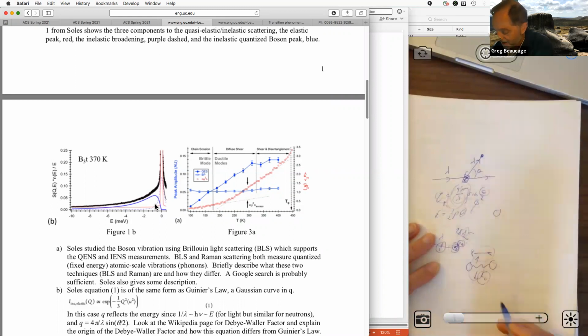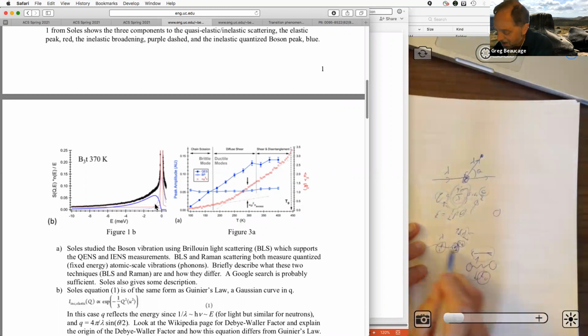So if the beam comes in and it's about the same energy as that vibration, then it can either, if that thing's already vibrating because of kT, give up that energy. So you can have your peak here, and then it can get a higher energy, right? That's called anti-Stokes. And it can also absorb the energy, so it'll shift down. That's called Stokes. So it's more likely to get a Stokes than an anti-Stokes. In other words, losing energy to the beam is easier than gaining energy from the material. Right, so you're more likely to get a Stokes, so that's a bigger peak.